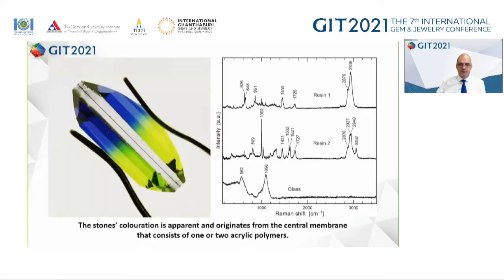So we have two glass halves that are stuck together around a very thin foil or membrane, only a few 10 micrometers, that consists of acrylic polymers. So it's like some kind of scotch tape in the middle, intensely colored. And when you look from the side, you can easily see this is colorless. And as I said, from the Raman spectrum, you can also see again it is a simple glass. So this is really, as I said, cheap material.